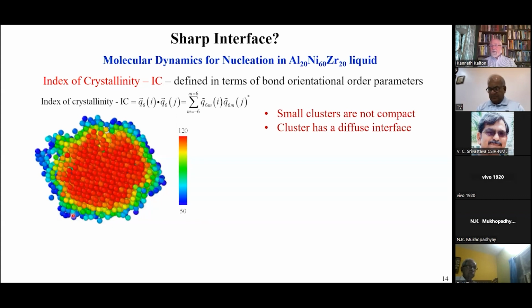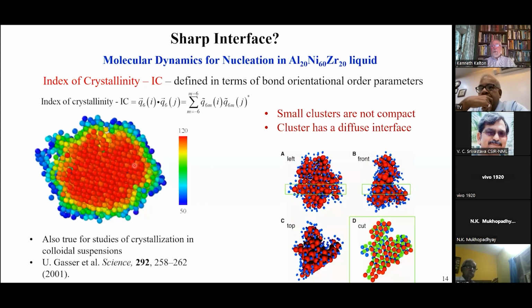Now, two things you find out from these calculations immediately. The cluster is not particularly compact. I mean, you could argue it's somewhat compact, but this is a large cluster. If you look at small clusters, it's very non-compact. It's almost fractal in its boundaries. The other thing is, it does not have a sharp interface. You can see there's a gradation in going from the center of the cluster to the edge of the cluster. So there's a continuous ordering process as you go towards the center of the cluster. So that Gibbs assumption is incorrect. This has also been found in studies of crystallization in colloidal suspensions. This is a rather old paper, but it was a classic paper that showed from those studies, again, the non-compactness of the clusters.